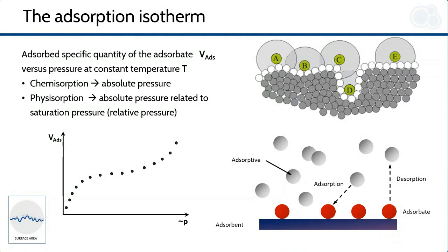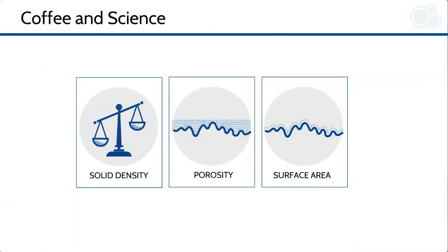Physisorption is a phenomenon that involves a higher density of gas molecules in proximity to solid surfaces, due to the interactions of the molecules in the gaseous phase with the free surface energy of atoms and molecules in the solid interface. At a certain relative pressure below 0.3, a monolayer of molecules covering the surface can be determined using some theoretical model, the BET being the most used. The BET model applied in a range of relative pressure typically between 0.05 and 0.3 gives the number of molecules covering a monolayer. Knowing the molecular dimension of the gas, it is possible to calculate the total exposed surface area of the material. We'll now present the results of these techniques applied to freeze-dried instant coffee.